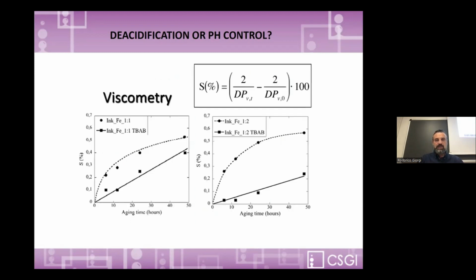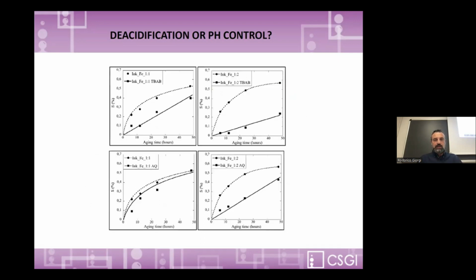If we measure, thanks to measurements of polymerization degree and evaluating the percentage of broken bonds, as we usually do for a kinetics study of the degradation process, we can see the benefit we have thanks to the application of antioxidants. We see that the curve has a lower slope, a significant reduction. We can see, comparing these graphs, that obviously we also have some benefit simply by washing the paper. But this is because we remove the iron excess. And for that, paper is more resistant under this condition.